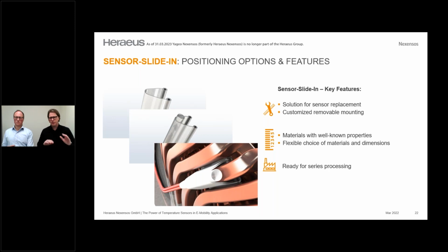That means the situation is really well connected. The surface is pressed down together, so our sensor is in very close contact to the hairpin, and this leads to a very good response time. And if you have trouble with a sensor, which is typically not possible with a real sensor, you can open that e-motor housing, plug that sensor out and mount a new sensor in the same way. In historical mounting devices this is typically not possible because they work with glue, with some very special materials which are sticky, and in the end they are hard and brittle. This is, in our eyes, a very good solution which we can show you.